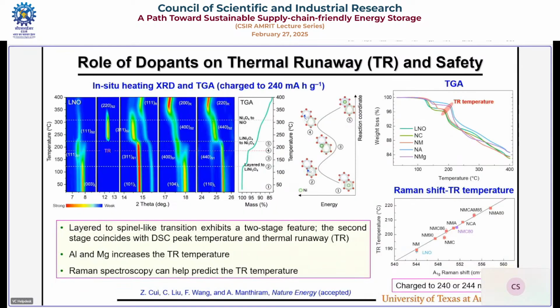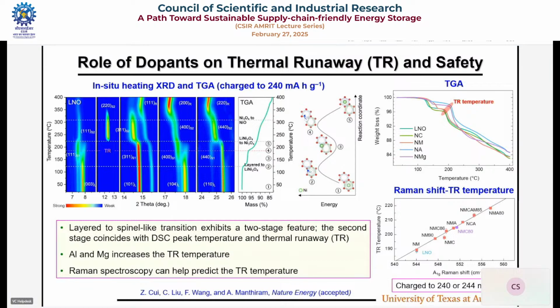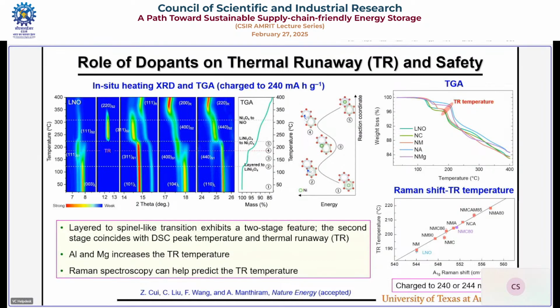We have also done synchrotron radiation. The way they lose oxygen is they form two spinels, LiNi2O4 first and then Ni3O4. The thermal runaway safety issue happens when it forms this spinel, and that is this. There is a good correlation between the thermal runaway temperature and the frequency in the Raman spectroscopy. So if you do not have a DSC but have a good Raman spectrometer, you can get the frequency, and then you have an idea whether the thermal runaway temperature is higher or lower. So it's good.